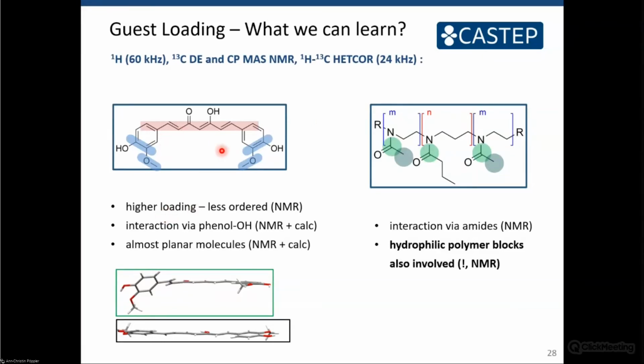And what we found just from NMR was that if we load more and more of this compound inside of the polymer, it gets less ordered. So we have no crystallization nuclei starting to progress or forming domains like in the previous example. With calculation and NMR, we found that these polar groups on the outside are the main hydrogen bonding partners, and that this enol is happy by itself. And we found also that while in the crystal structure the molecules are twisted, like in this green example, inside of the micelles they are more planar. So this twist is less strong.